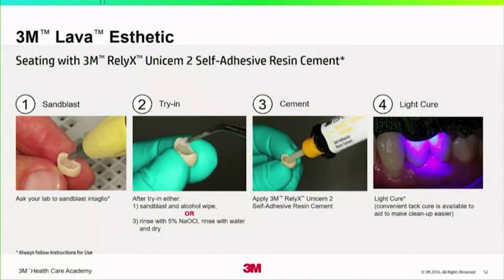I use a light curing instrument that has a 1-second timer on it. And when I use it with Unicem 2, 1 second's perfect. I can peel the cement off nice and cleanly, let it set in the auto cure mode, and you're done.